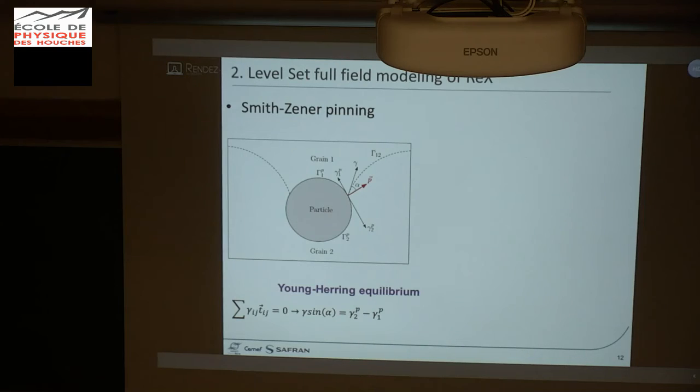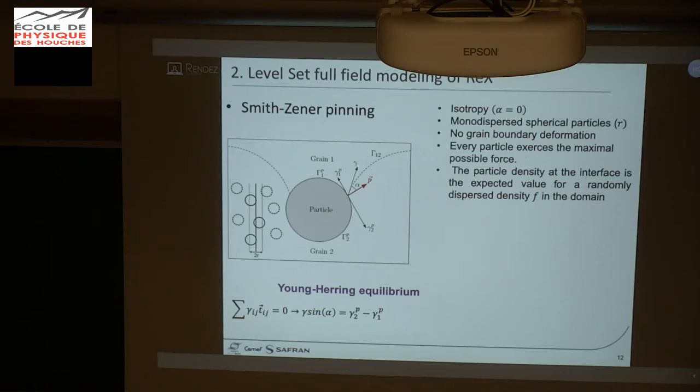By respecting this equilibrium, you will of course modify drastically the local curvature of the grain interface, which is responsible for the pinning of the grain interface by the second phase particle. Now, if you use all the assumptions used by Smith-Zener, you will obtain different equations for the definition of a driving pressure due to the presence of the second phase particle.